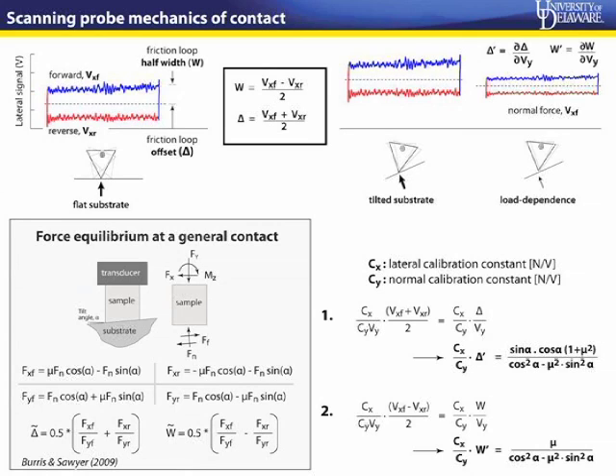Let's take a moment and look at the basic mechanics of contact of an AFM tip. If you have a loaded AFM tip on a flat substrate, and you start reciprocating motion, there will be torsion about the shear center of the cantilever, and you will end up with a conventional looking friction loop. In the friction loop, you will have the forward signal and the reverse signal, which is essentially made up of the translation of the tip on the surface. In the friction loop, there are two quantities which are pertinent to be mentioned here. The friction loop half width, which is essentially a qualitative measure of friction at the interface. And the second is friction loop offset, which on a flat surface may or may not be zero. Mathematically, W, or the friction loop half width, is half of the absolute width of the friction loop, and delta, or the friction loop offset, is merely the average of the forward and reverse signal. Again, remember, these are raw signals of the AFM, so these are in volts.